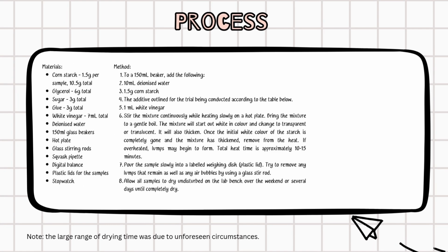For the method, each bioplastic sample was made by heating a mixture of cornstarch, water, vinegar, and a set combination of additive. One is glycerol only, half glycerol and sugar, and then half glycerol and PVA glue, on a hot plate for 10 minutes. Once the mixture turned translucent, the sample was then poured onto a dish and dried for between 3 to 21 days.